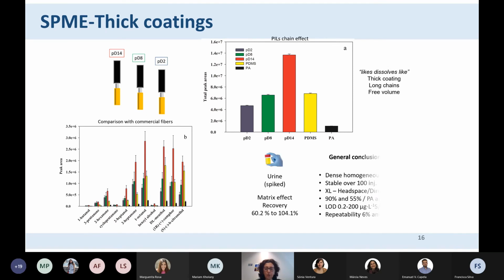And so let's take a look at the results. Here we compare our fibers, the top three, with the commercial fibers, the yellow and the black. So we are comparing polymeric fibers with polymeric fibers. And we used a bunch of standard compounds to compare these fibers. What we can see here in the total peak area is that we absorb more compounds than the commercial fibers. What we can see in this lower graph, by comparing each one of the compounds, is that it looks like we are typically sorbing more, at least the P when we have a carbon 14 in the side chain, that it sorbs more compounds than all of the other fibers.